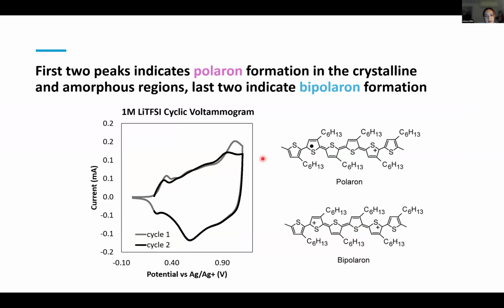We get pretty good reversibility between the first and second cycle. And we see that the 4 peaks that we see in the first cycle are still there on the second cycle. So this is evidence that our air-free setup is working.